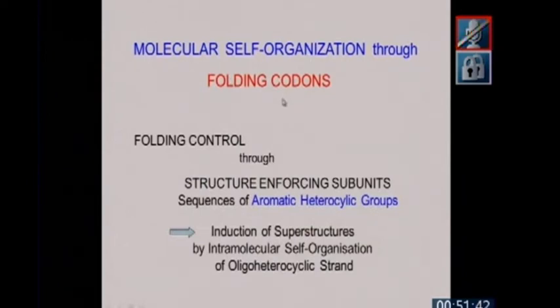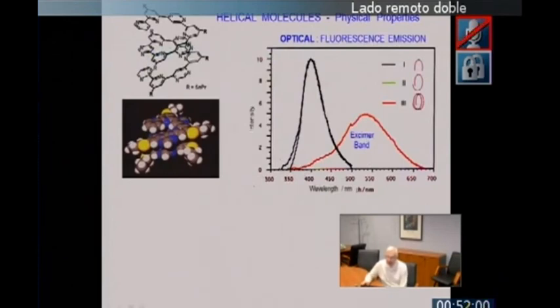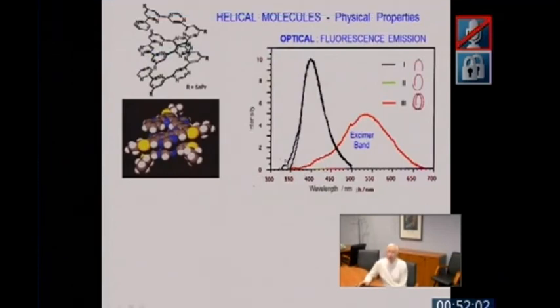And we have developed this quite a lot. You can define what you can call a folding codon, meaning that depending on the sequence of heterocycles, you obtain a different shape of the resulting molecule. In terms of properties, something interesting occurs. Just to mention one: as long as the chain does not overlap, you have a normal fluorescence emission. But as soon as the chain overlaps, as shown here in this 2 turns helix, a new band appears, which was an excimer band due to the overlapping of the conjugated pyridine units in this structure.